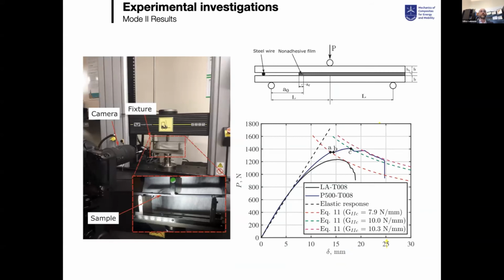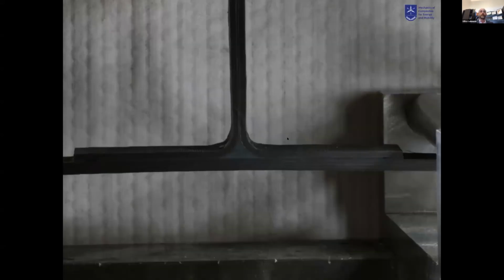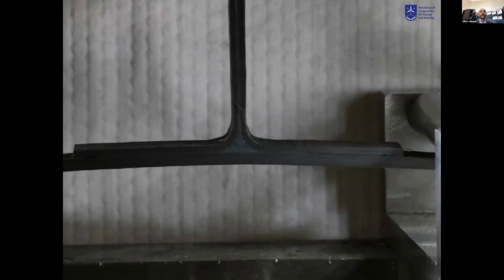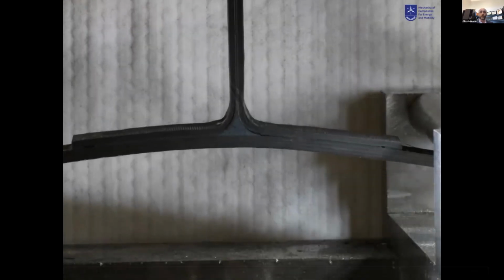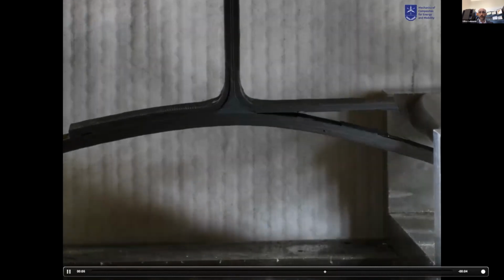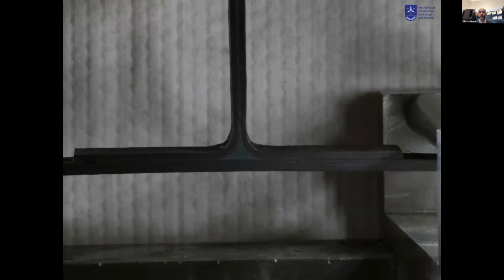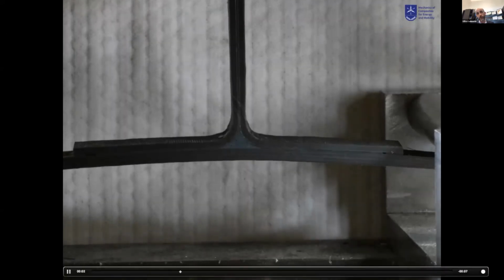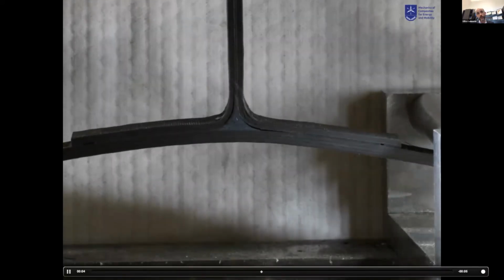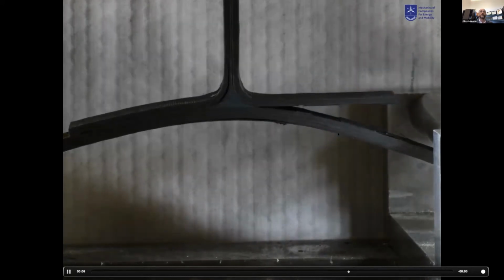So this is the first thing that I wanted to share with you. It's something that has been demonstrated in mode 1. It has been demonstrated in mode 2. You can see on a small structure like this, like a T-joint reinforcement, that if you make a surface treatment like this at the interface, you are going to create something like ligaments during the failure of these T-joints that are usually stiffeners used for composite structures.